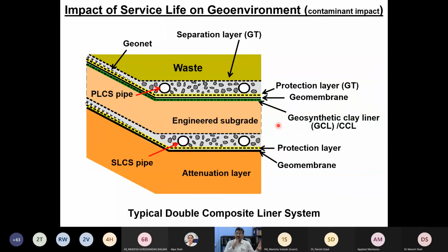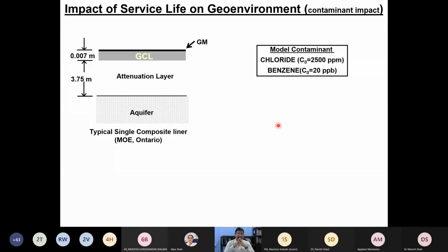We go back to the same liner. Just for the understanding point of view, I have considered a single liner system here: a geomembrane, a GCL, an attenuation layer, and an aquifer. By changing the service life of a geomembrane, how do model contaminants, an inorganic contaminant such as chloride, and an organic contaminant commonly present in the landfill such as benzene, get transported within the liner system if the membrane is aging over a period of time?